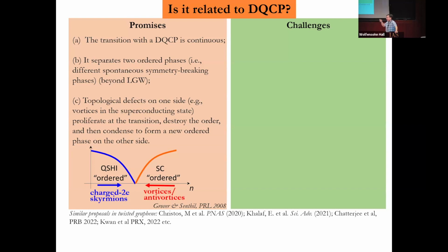This very much looks like what I was trying to describe, right? In this specific case, what they want is an ordered quantum spin Hall state. There you also have a topological defect if you go to the other side. The topological defect is a charge 2e skyrmion in this quantum spin Hall state. And just like vortices, they condense at this point to give a superconductor. So experimentally, we are probing the vortex and anti-vortex. This half we have experiments for. And then we have a puzzle of why the sudden death. I think if we can somehow find evidence of this charge 2e skyrmion, then the story will be much more convincing. But what really happens here is still an open question.